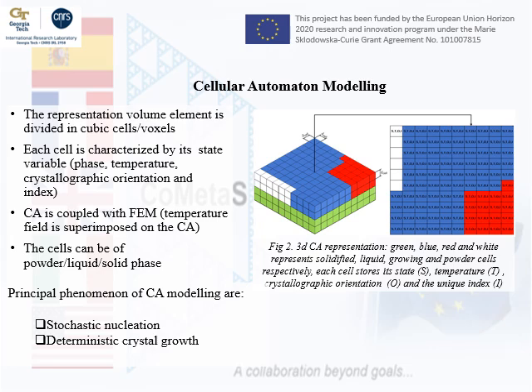And to this aim, we also utilize finite element simulation. So we pre-calculate the temperature field imposed on the microstructure, and then we simply couple together these two types of simulation, right? On one hand, we first simulate the temperature, we impose the temperature onto the cellular automaton, and then that temperature is going to influence first the melting of the powder, and second is also going to cause the driving force for the crystallization and also the growth of the crystal during solidification.